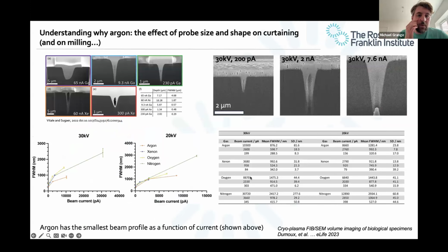Now, why is that? Well, on the top left, you can see the beam profiles. In this case, you essentially do a spot burn in silicon. So you mill using a single pixel of your probe, and essentially then fill that up with something you can image, such as organoplatinum. And you can see that there's a relatively shallow full width half maximum with gallium. On the right, you can see the case for argon.